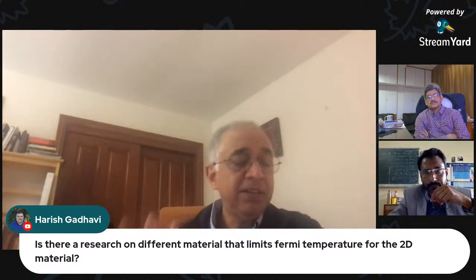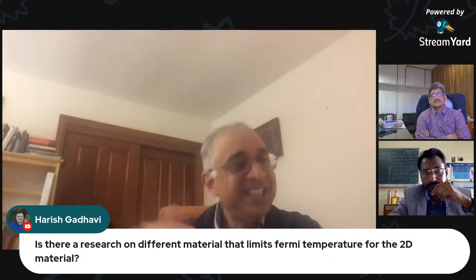And what they do is, again, trying to change the chemical potential is very hard in a metal. But they looked at semi-metals. And in semi-metals, by doping, you can easily change. So these are very narrow gap semiconductors where the bands have slightly overlapped and you get some conduction. So he has been able to also see experimentally the BCS-BEC crossover there. And in magic angle twisted bilayer graphene, again, by gating, people can change the carrier concentration.